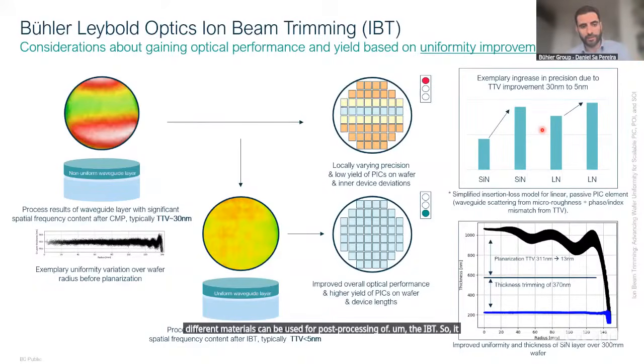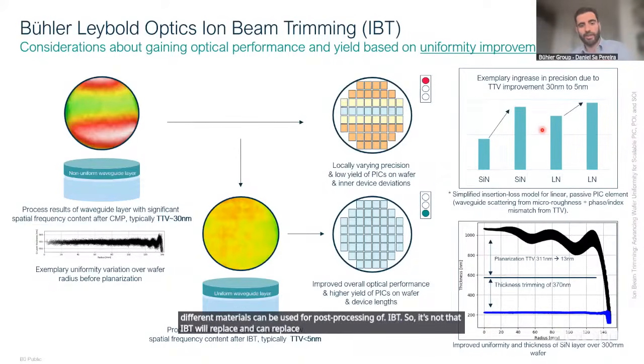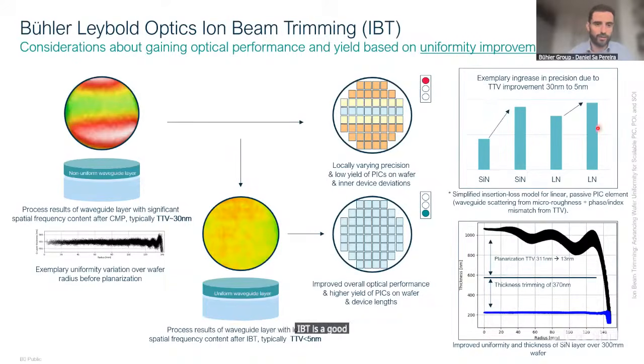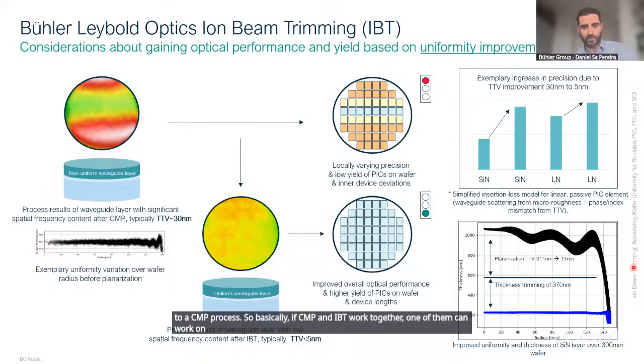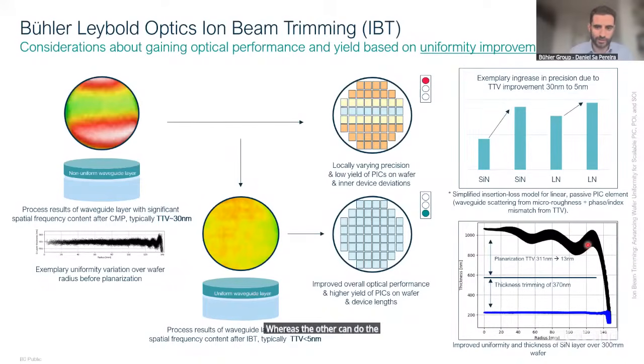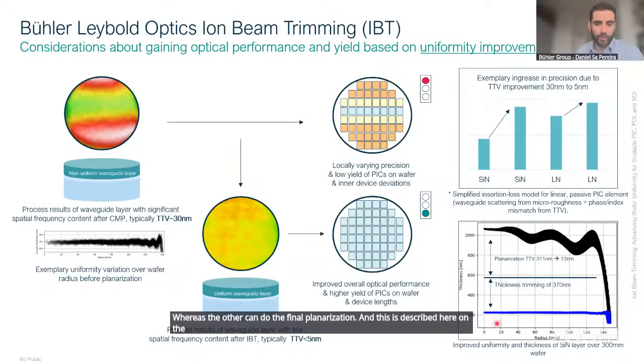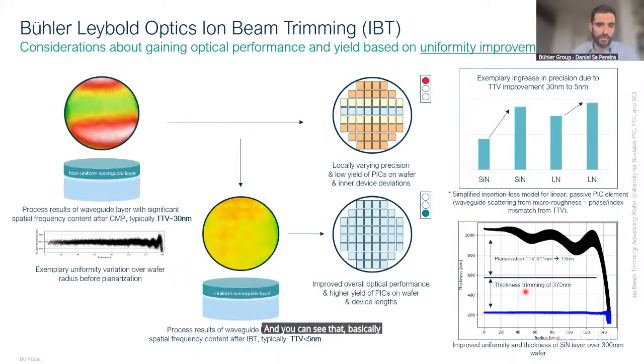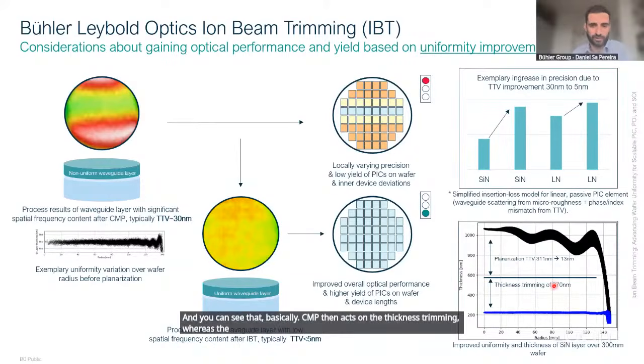So it's not that IBT will replace or can replace CMP, it's that IBT is a good add-on to a CMP process. So basically, if CMP and IBT work together, one of them can work on the volume removal of the material, whereas the other can do the final planarization. And this is described here on the thickness deviation within one 300 millimeter wafer. And you can see that basically CMP then acts on the thickness trimming, whereas the IBT will act on the planarization.